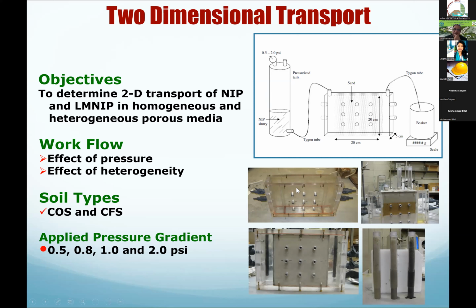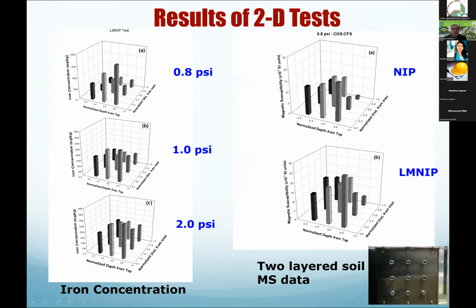This is a simple plexiglass cell. As I said, you're putting the solution in at the bottom here, and then it's coming out. Again, the top is sealed completely, and then you can pressurize it, and it's coming through, and you have these ports through which you can collect samples of the pore water and analyze them. So this is how these things are. Basically, we ran the tests under different pressurized conditions, using the bare nano iron particles and lactate amended nanoparticles. We created uniform sand layers, and we also created layers to look at the effects of heterogeneities.